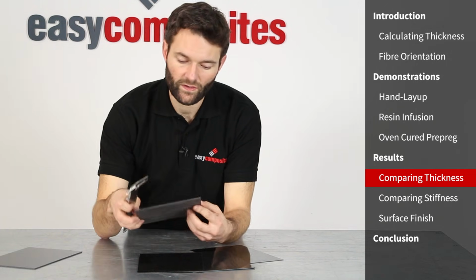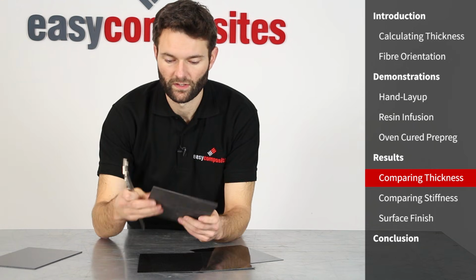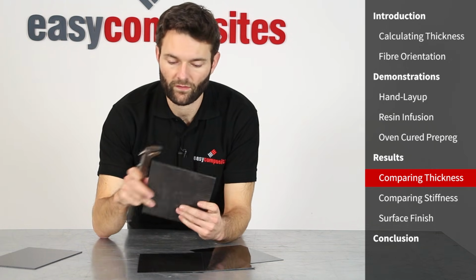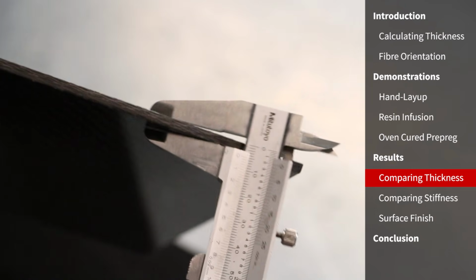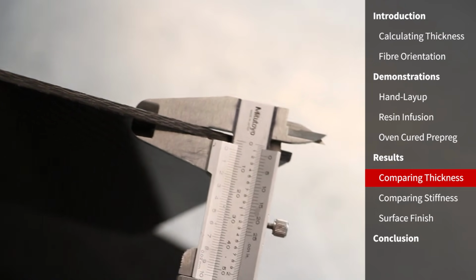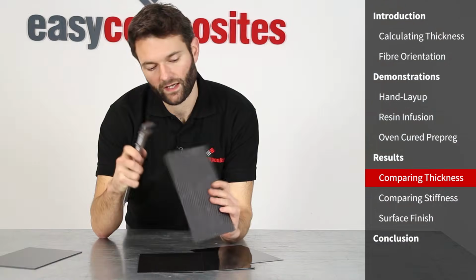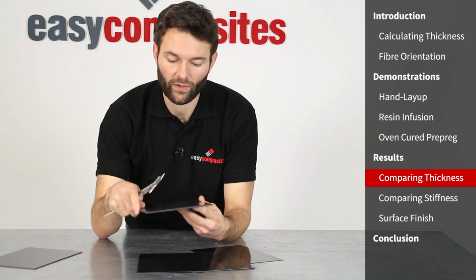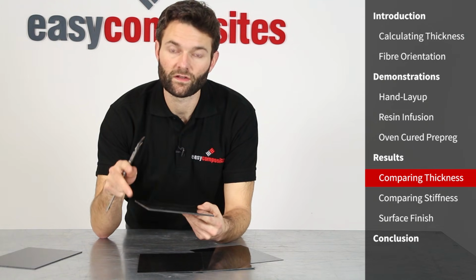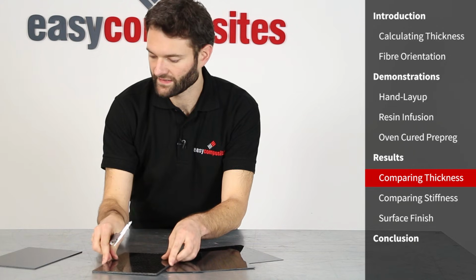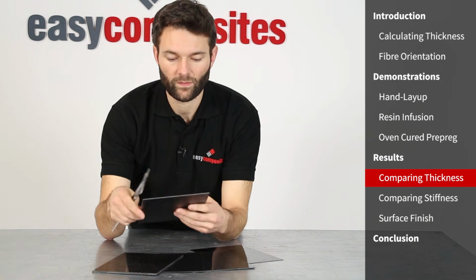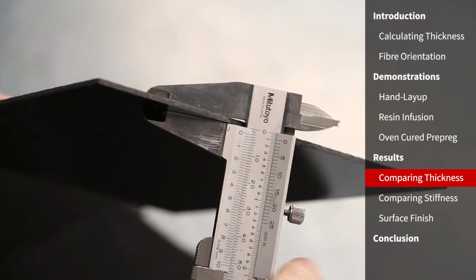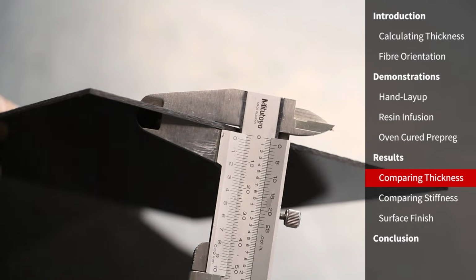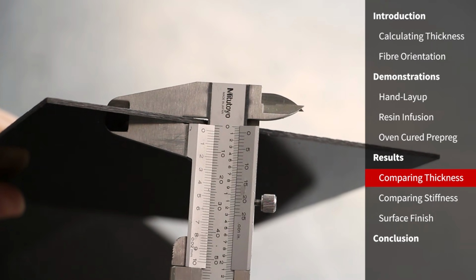We did a second infusion, this very, very strong, sturdy 650 gram. Now this is coming up at around about 4.1, and we were anticipating around about 3.9. So again, very close to the consolidated thickness that we'd expected. And finally, we did the prepreg sheet. Have a look at the thickness of that, around about 2.2 millimeters on that one.